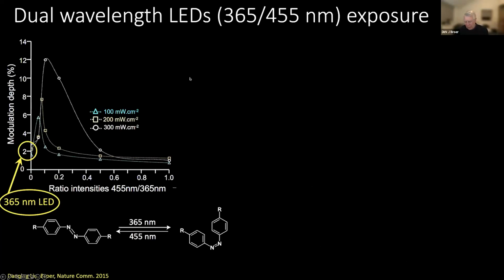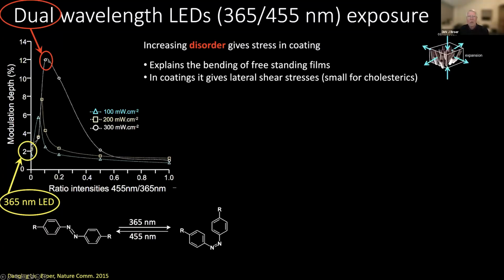And what appeared to be very important is that as soon as you add a second wavelength, the wavelength that is basically responsible for the reverse reaction of the cis to the trans state, we could boost the surface deformation to much higher values. So the mechanism that we now have under discussion is that the increasing disorder originating from the trans to the cis state gives stresses in the coating, and that might explain bending in the freestanding films, as we saw before, and it gives some lateral shear stresses, which are also responsible for this 2% deformation.